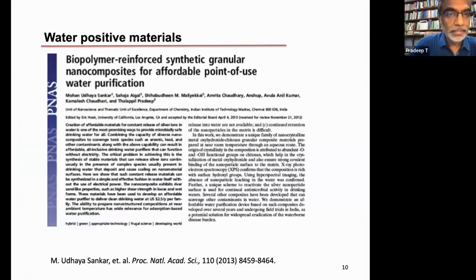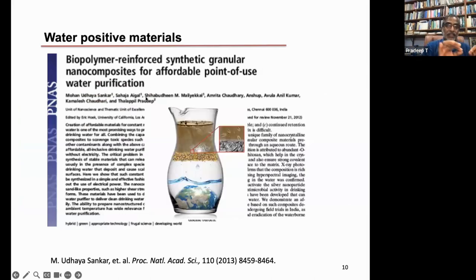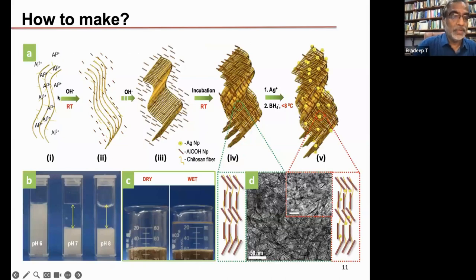These materials, in technical terms, are composites. They are biopolymer reinforced composites. So what we do is such composites are used as templates over which nanostructures of what are called oxyhydroxides are prepared. And this preparation happens in solution. So you have biopolymers over which a metal ion, such as aluminium, or it can be titanium, or it can be iron, are deposited as oxyhydroxide of this kind of a formula. And this is then incubated for some time around room temperature in Chennai. From solution, this is all in solution, you create a solid material and you can put water over it, and this material is still stable.